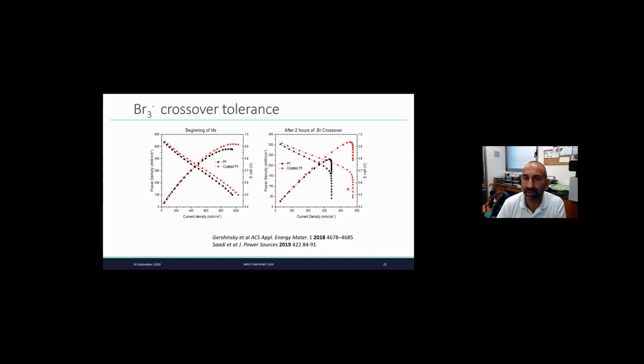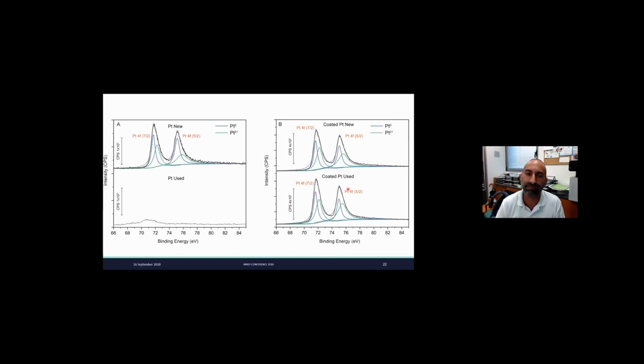So we did some publication about it and we are pretty happy. But we had some questions about the polymeric structure of the polydopamine. It's too complicated for us and we don't know how to address this issue. And it's really an open question. What is the structure? And when you don't know the structure, the problem is that you don't know how to make it better. So that was the XPS showing that after some time, if you don't have any coating, then you don't have any platinum anymore.